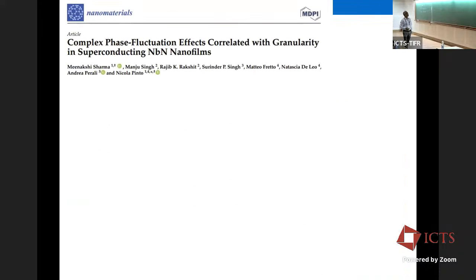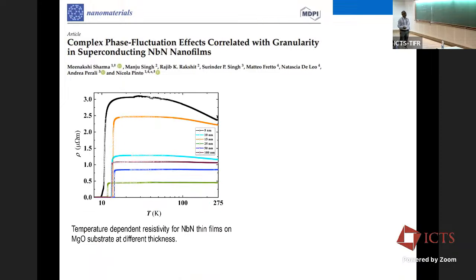Okay, out of this optimization work of Nb thin film, we published recently this paper on complex phase fluctuation effect correlated with granularity in superconducting nanofilms. Our theme was not towards the device, but towards the fundamental physics. So we were looking for some kind of quantum phenomena in there. Here, as you can see, we deposited Nb thin films on MgO substrate with different thickness of the film. Your TC varies. So this is what I mentioned before, that this is one of the parameters where we have to control the TC. However, even for a 5 nanometer thin film, we are getting a TC around 9 Kelvin in here, right?